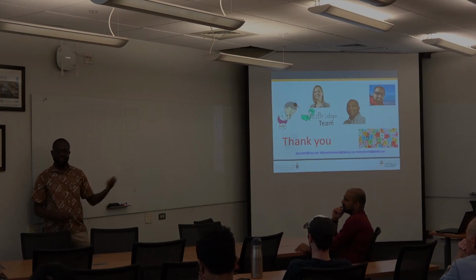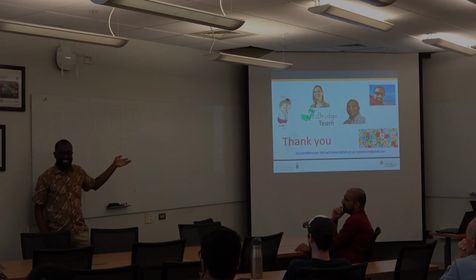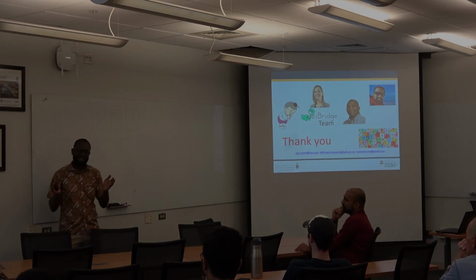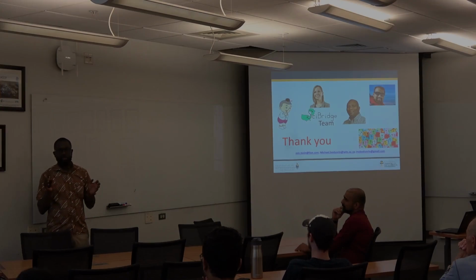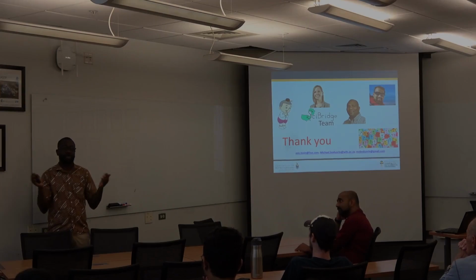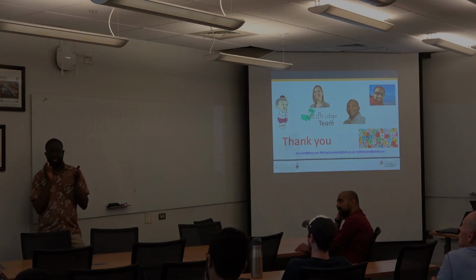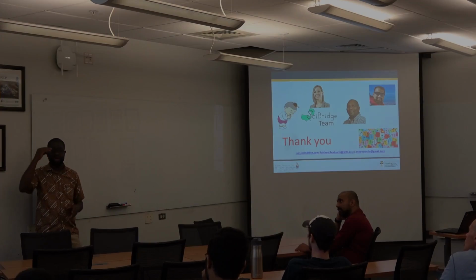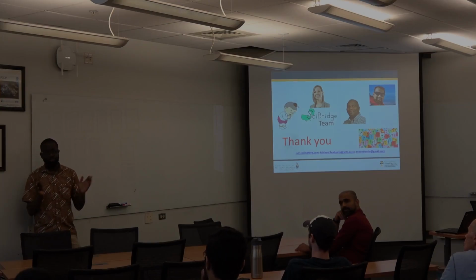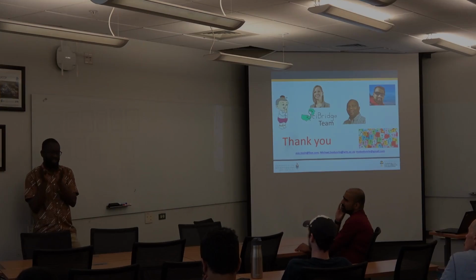Okay, so like I said, we did this with very little resources. The reason we stayed at 3 to 5 was because we actually did a lot of literature search, and they reported that as the optimum. The argument is that when you go beyond 5, you start finding some crazy carbides, and that also brings it down. So we kept the work within the compositions reported in the literature. But it would be nice to really confirm.